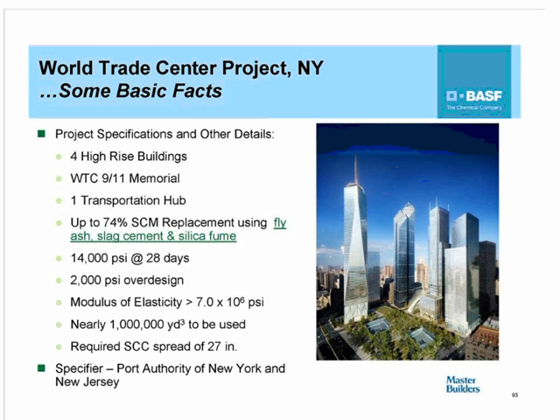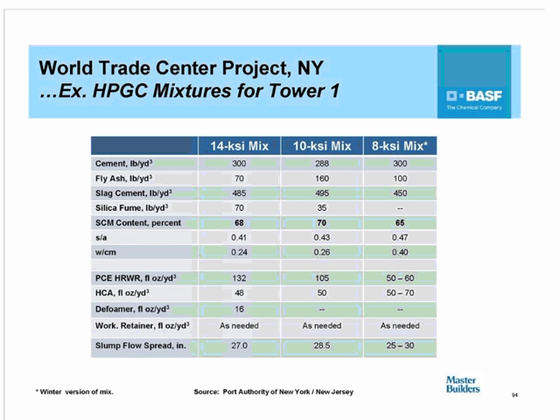And what is unique about the concrete that was used in this project was the fact that up to 74% of the Portland cement was replaced with supplementary cementitious materials, a combination of fly ash, slag cement, and silica fume. The concrete was designed for 8,000 psi, 14,000 psi in some of the applications, but they ranged anywhere from 8,000 psi to 14,000 psi. And all of it was basically self-consolidating concrete. And as we can see here in this particular mix design, the supplementary cementitious materials for the 3 mixes shown here ranged anywhere from 65% to 70%.